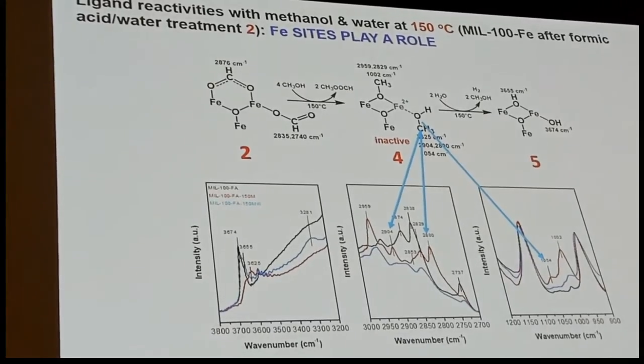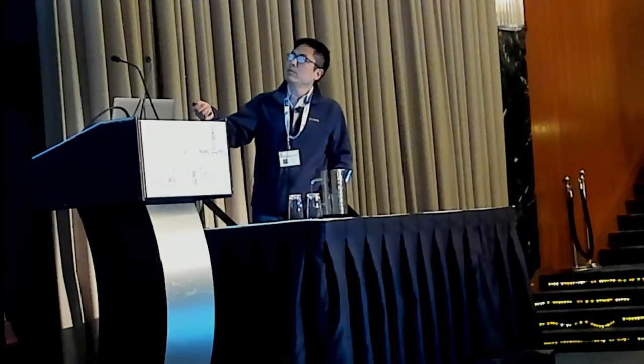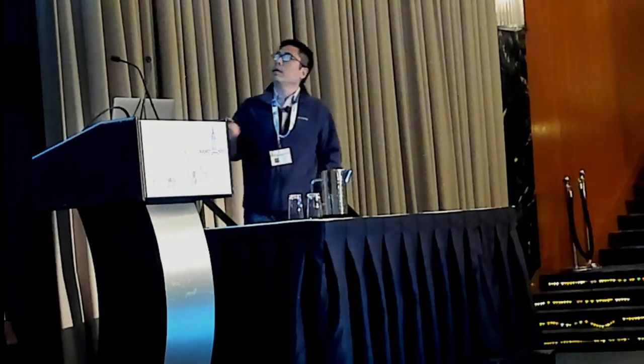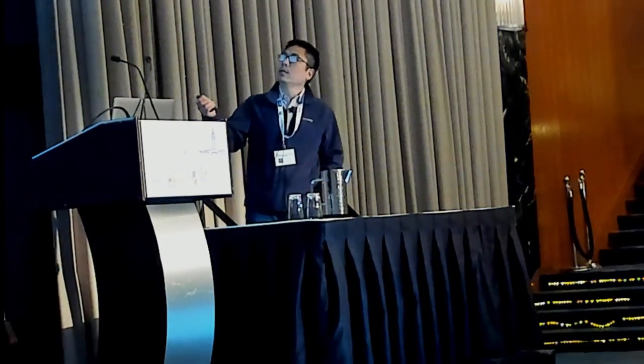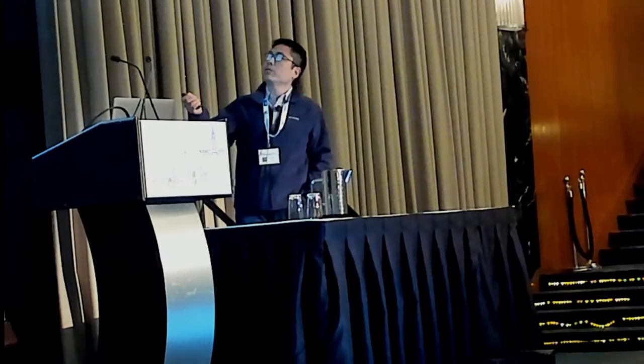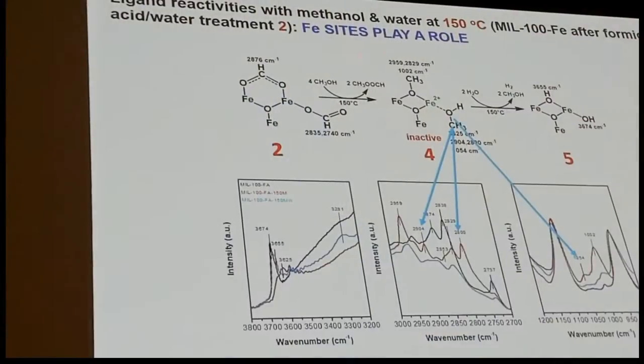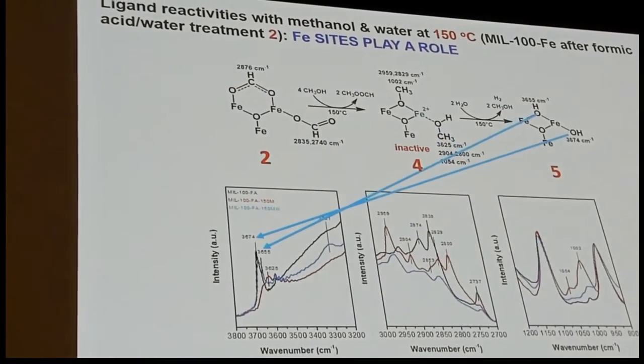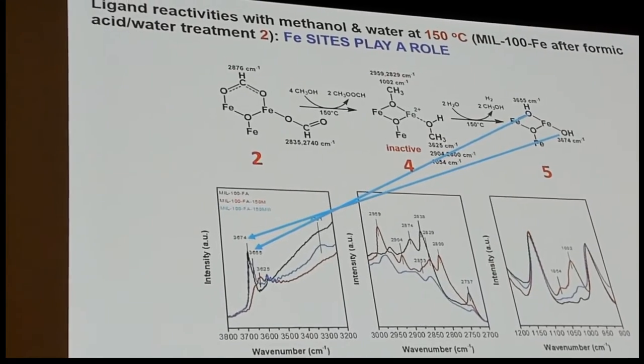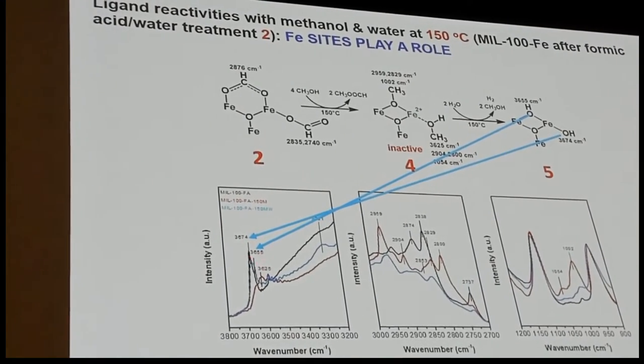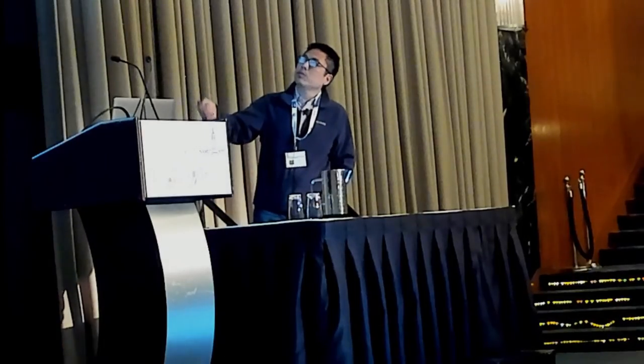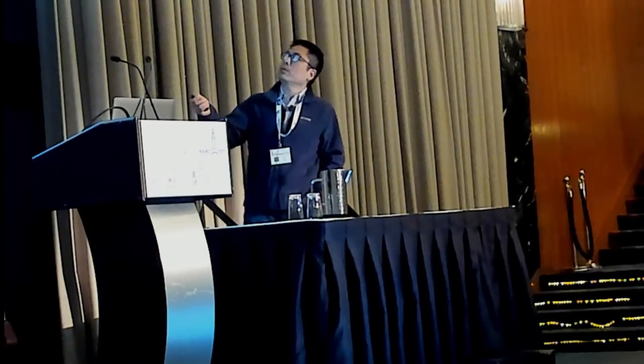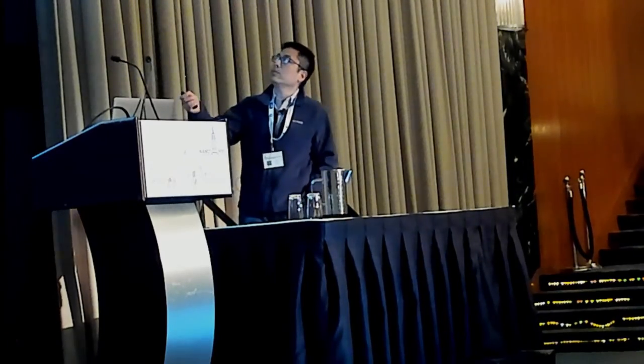What we observe is a band in the low C-H stretching region, which we assign to methanol bound to iron²⁺. That means iron was reduced from Fe³⁺ to Fe²⁺. In this case, we don't have two methoxy groups together, so we lose the activity. When we treat the sample with water again, we see both µ2-OH and terminal hydroxyl groups reappear. That means Fe²⁺ was re-oxidized by water back to Fe³⁺.